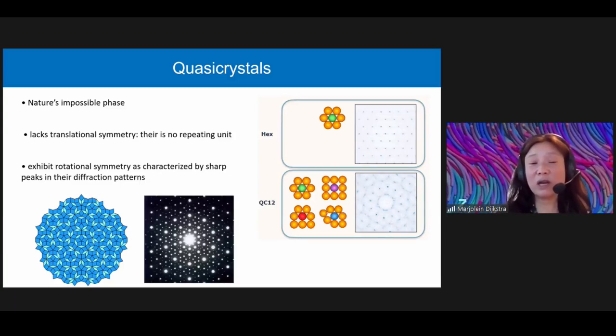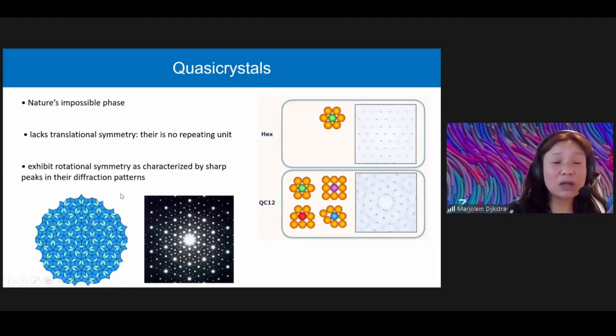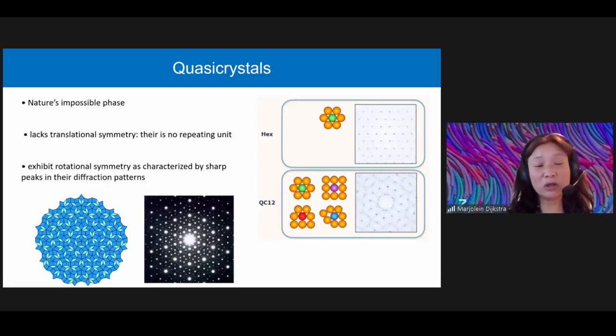So it's not like a crystal where if you know the unit cell, you know exactly where all the other particles are. In the case of the quasi-crystal, it is not known where the atoms or particles are. If you look at the diffraction patterns of a quasi-crystal, it shows very sharp Bragg peaks with a rotational symmetry that is actually forbidden from a crystallographic point of view. So this is a nice challenge to inverse design a quasi-crystal where you do not know where